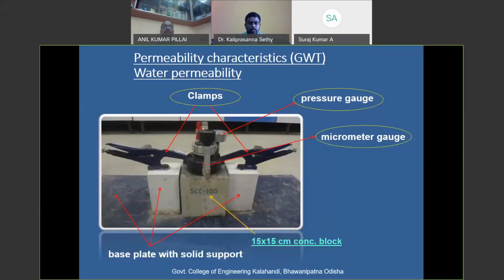So here is the test which is performed by this German water permeability testing apparatus. As you know, durability is highly influenced by permeability, because the ingress of external aggressive ions affects your concrete. So we have to take care of our concrete by checking all the parameters like permeability. For that, we have conducted this German water permeability test. You can see from the diagram.